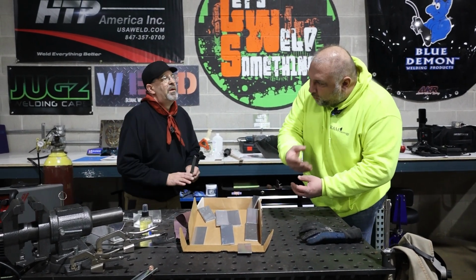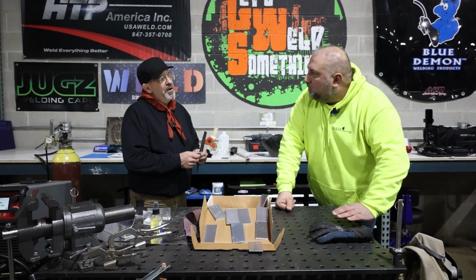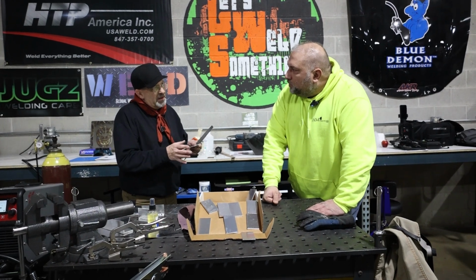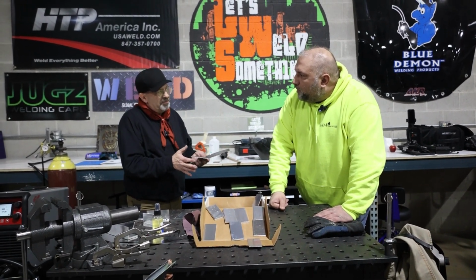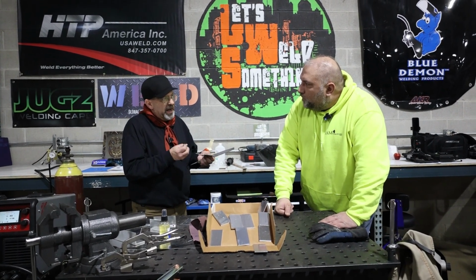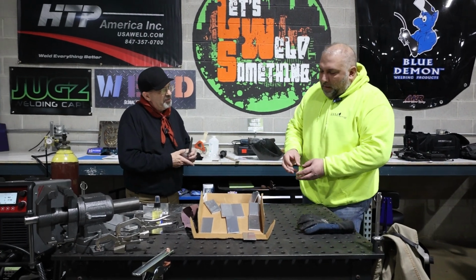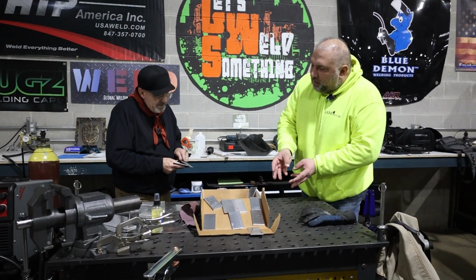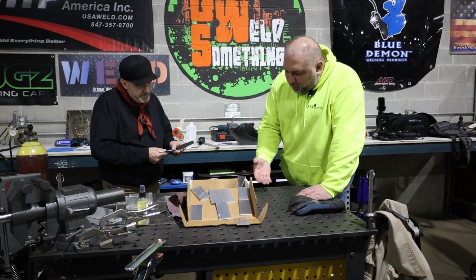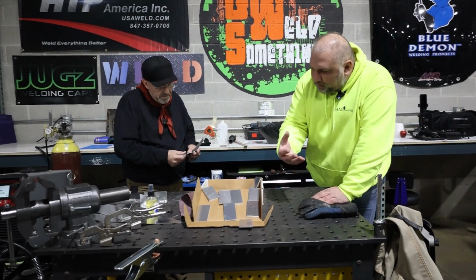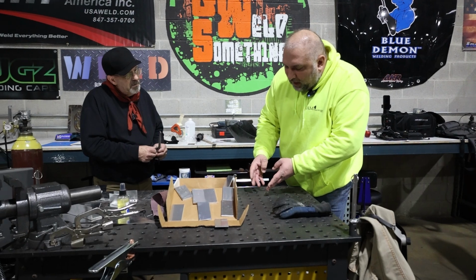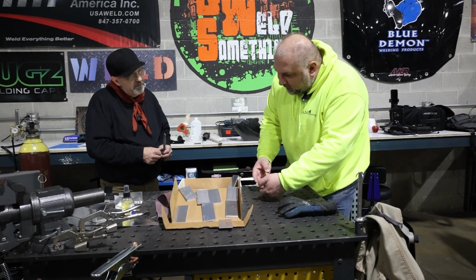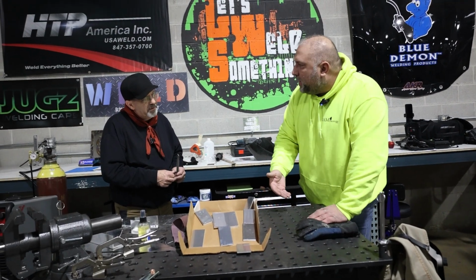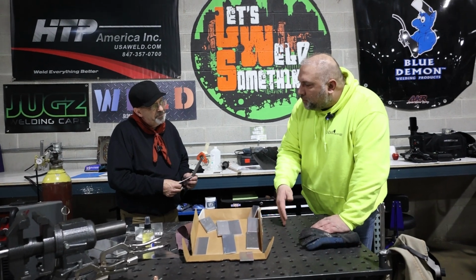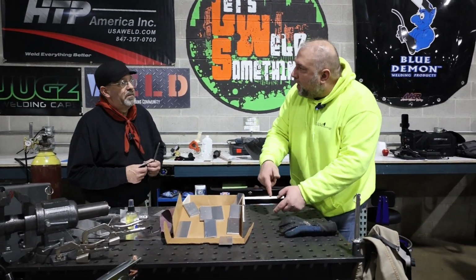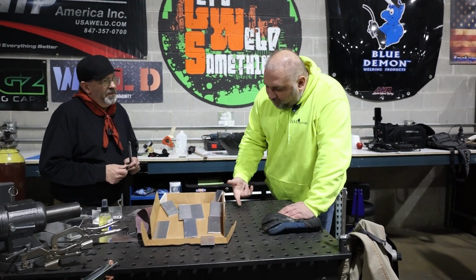It blasts the impurities away. But isn't the argon inert, not ionized to a point where it's doing anything? It's protecting the weld pool, protecting the material, but there's no real reaction with it. It's just a function of blowing the contaminants away to a degree. That's why the pushing action of the gun helps you a lot more than pulling. Pulling, you're blowing the contaminants back into the still hot, potentially liquid weld pool. That's when you get black soot, pepper inclusions, pinhole inclusions, blowing it back on top of the molten weld puddle. That's why you move forward in a pushing motion.